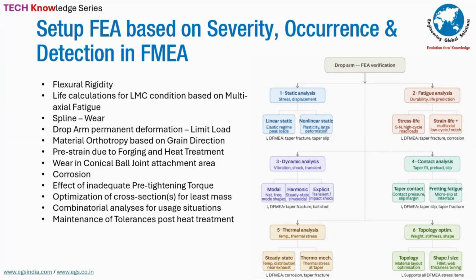We did have a drop arm calculation wherein one of our customers asked us, this drop arm, can you please predict and tell me whether it failed because of lack of pre-loading or because of a torture track issue. So we did the analysis both ways and we said it is not because of preloading, it is because of the cross-sectional modulus. And in this torture test track, between this cycle and this cycle, you can go and see the truck would have this component, this particular area, the crack would happen. They were shocked. We didn't know it. We predicted it. They came back and said, how did you do this? This is the process.